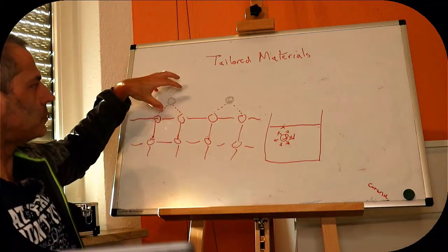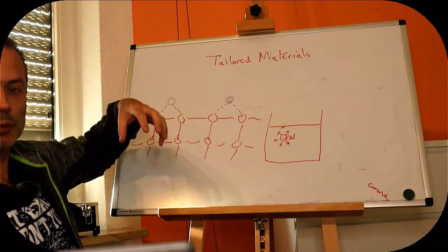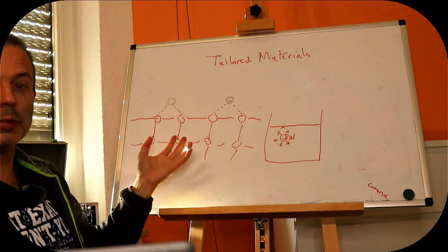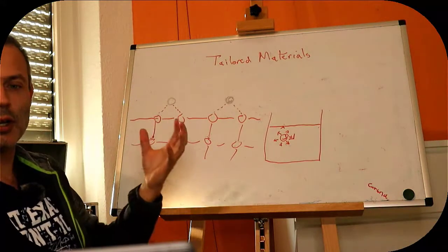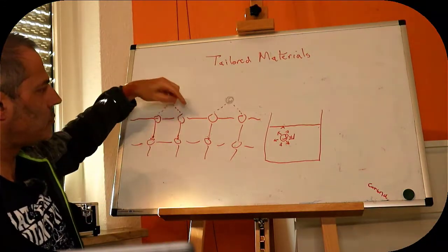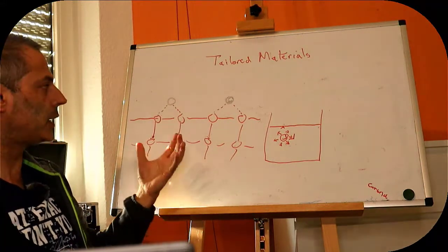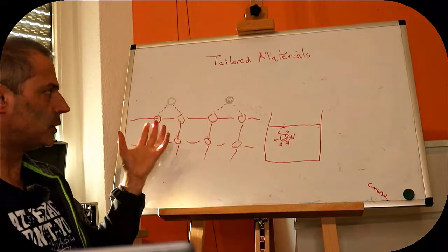And these atoms that we've added to the top can sit in between atoms of the surface, allowing the base material to relax. The ultimate version of this would be attaching hydrogens or fluorines, which only have one bond each, to the surface, which would enable something like silicon to relax back to its normal crystal structure, because we have now filled it all in.